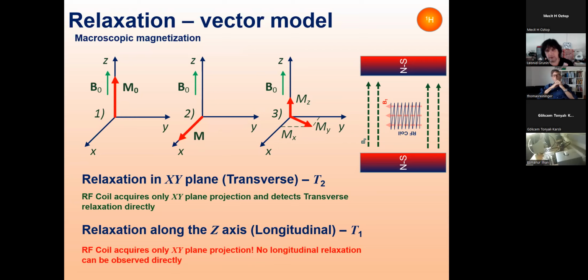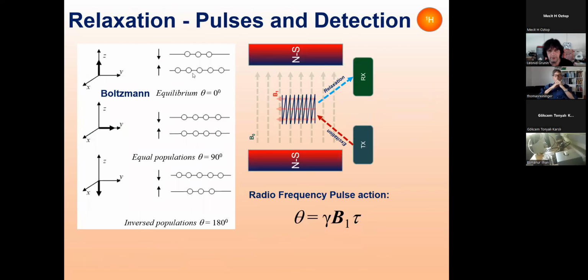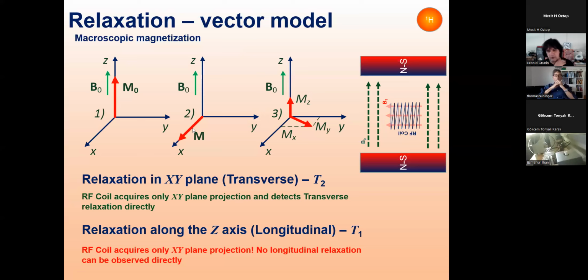So here, spin-spin, this is relaxation within the levels of spins. This is how they come to equilibrium. But when you excite the system, you understand that the system is not only quantum mechanical, this is a real material. And this excitation that we did with the transmitter must be dissipated into the structure, into the network, into the lattice of a sample to give rise to mechanical motion or rising of temperature and so on. So there are two types of relaxation: the relaxation within the spin system and the relaxation between the spin system and the lattice. Two types, and they are characterized by the relaxation times T2 and T1.